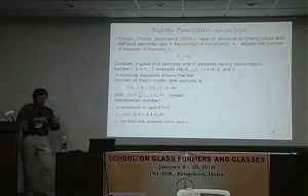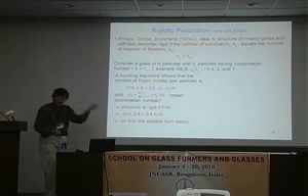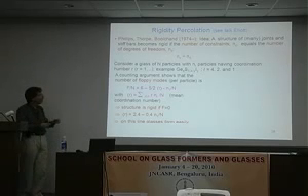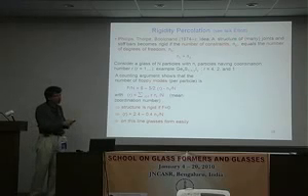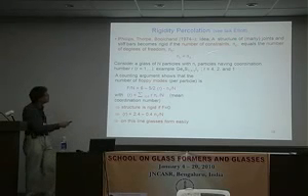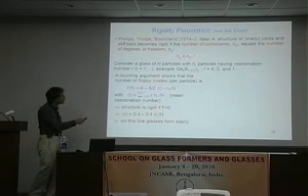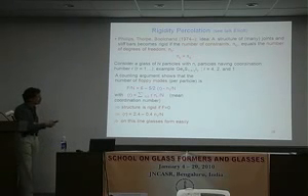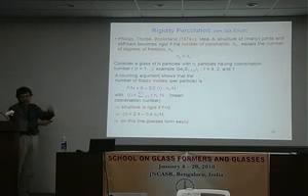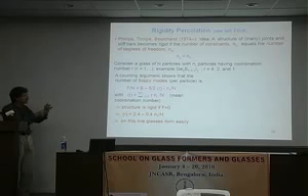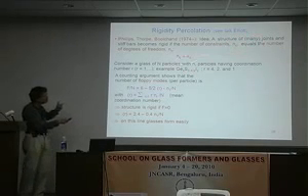And so it's a simple counting argument on how many degrees of freedom you have and how many constraints you have. And one can show that if you have many particles, if the number of constraints equals the number of degrees of freedom, the structure is rigid. Okay? If you have only few particles, you have corrections that are related to the dimensionality and that. But we are interested in many particles, and that's basically the result.